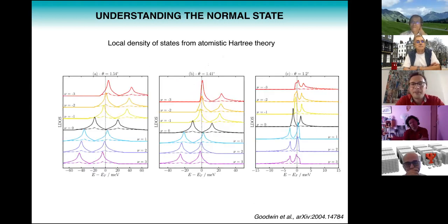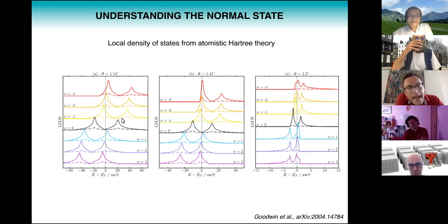Anyway, now I want to compare these measurements to our atomistic Hartree theory calculation. I'm showing you the local densities of states for 3 different twist angles, 1.5, 1.4, 1.2. So 1.2 is, of course, the one quite close to the magic angle, and this is as a function of energy with respect to the Fermi level. So 0 is the Fermi level. And I'm showing you 7 different doping levels. So nu is, again, the number of electrons that you have added or removed from the material. Now, let's start with 1.5, which is quite far from the magic angle.